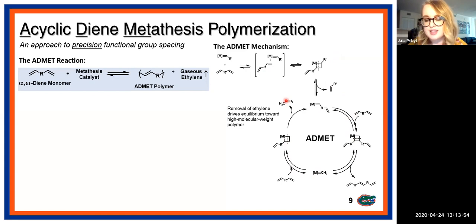ideally. And this is actually the way that we drive our system towards high molecular weight polymer, typically by applying vacuum to remove the ethylene gas. So one thing that Dr. Wagner likes to mention is that we can actually prepare unsaturated polyethylene by condensing ethylene, which is kind of counterintuitive, but that's the way that it works.